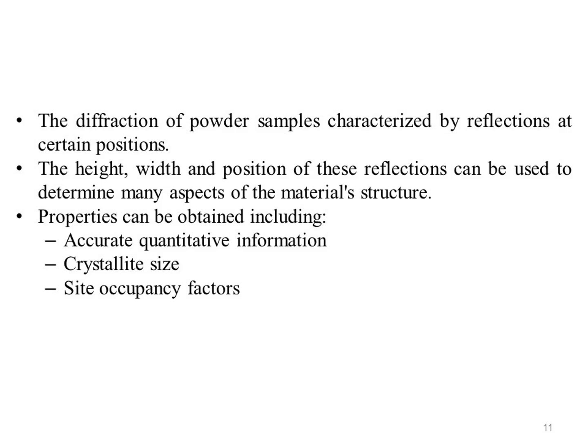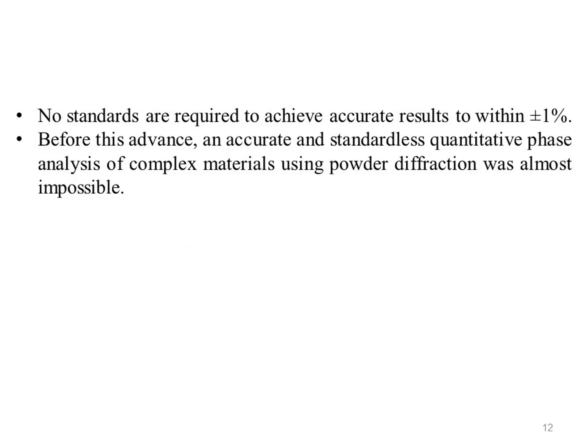The process of refining the pattern is computationally intensive, requiring several minutes to calculate results for a multi-component mixture. Rietveld analysis has the advantage over conventional quantitative methods that no standards are required to achieve accurate results to within plus minus 1%. Before this advance, an accurate and standardless quantitative phase analysis of complex materials using powder diffraction was almost impossible.